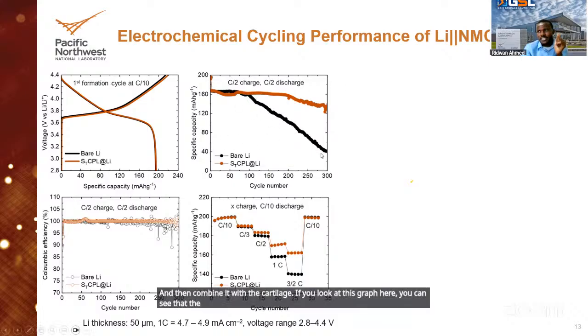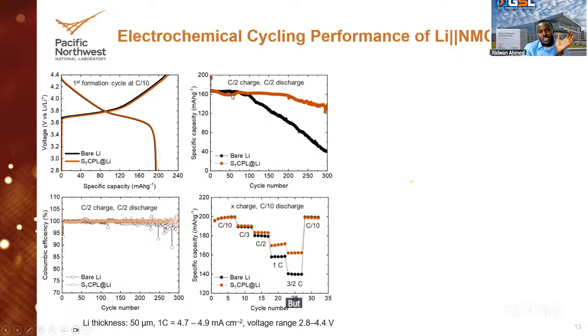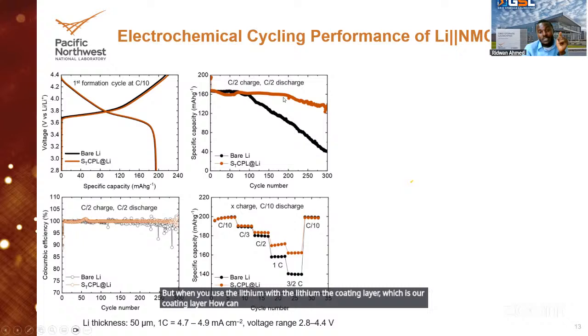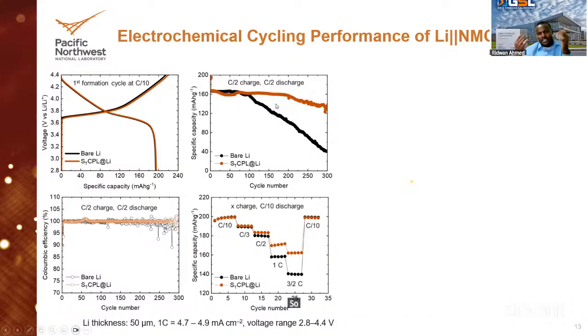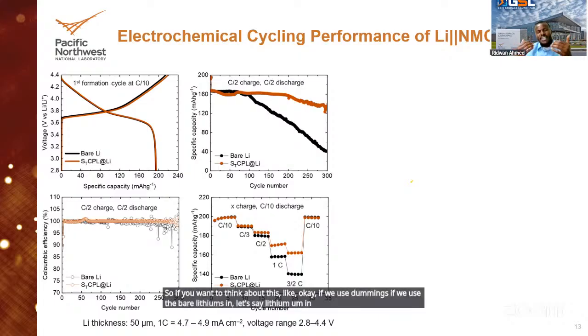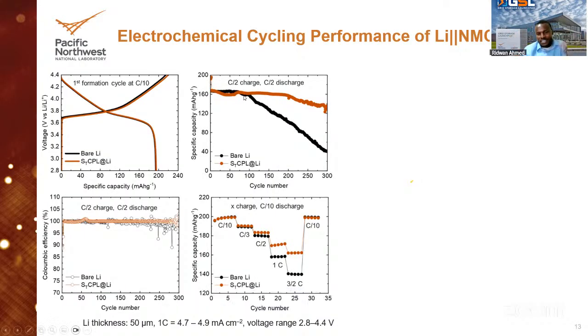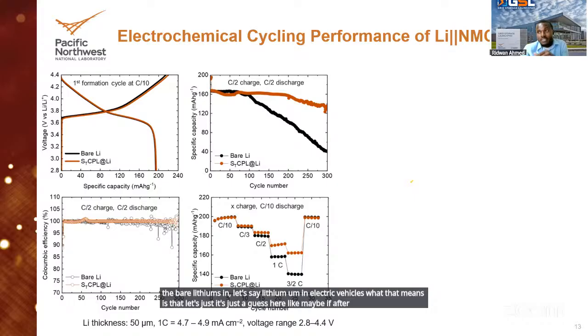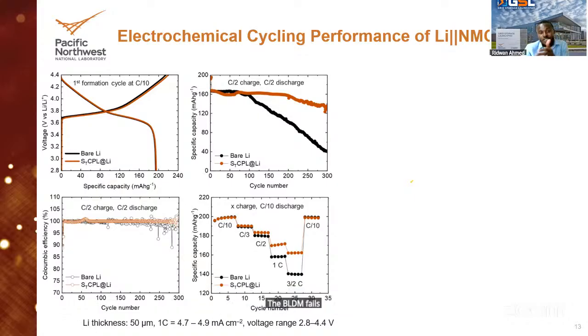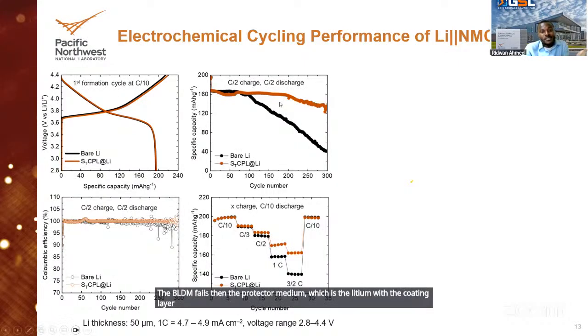If you look at this graph here, you can see that the capacity drops very fast. But when you use the lithium with the coating layer, which is our coating layer, it can withstand a longer cycle number before it starts dropping. If we use bare lithium in, let's say, electric vehicles, it's just a guess here, maybe if after 1 year the bare lithium fails, then the protected lithium, which is the lithium with the coating layer, can still work for an additional 1 or 2 years before it fails.